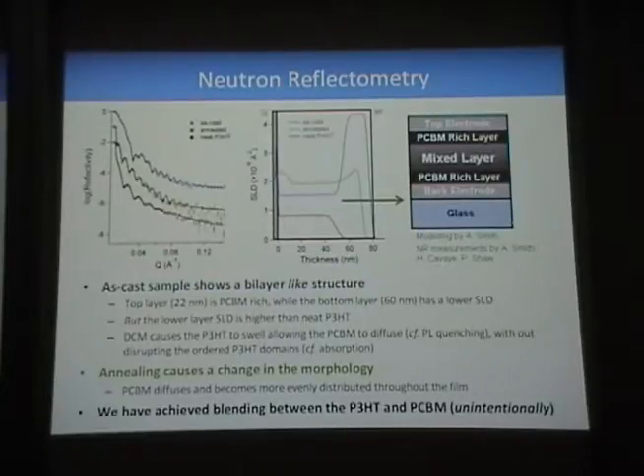From the profile, if you do some modelling, you can extract the morphology, and this is shown here. So the red trace is of the neat P3HT film. You can see that it's of the same SLD, so it's a uniform film. Now the blue trace shows the as-cast sample. You can see it shows a bilayer-like structure. The top layer, which is 22 nanometers, is PCBM rich, because the SLD is quite high, while the bottom layer, 60 nanometers thick, has a much lower SLD. But the important thing here is that the lower layer SLD is actually higher than the neat P3HT. So it's not pure P3HT on the bottom.